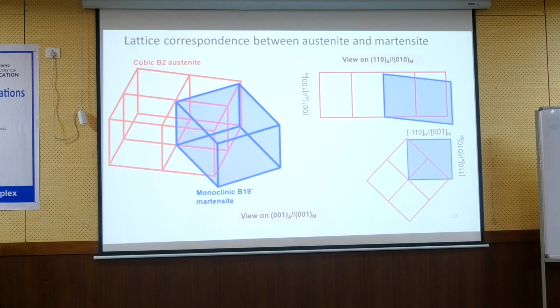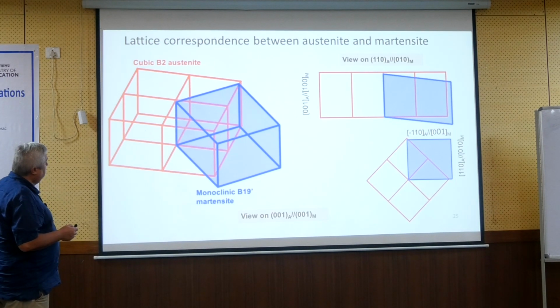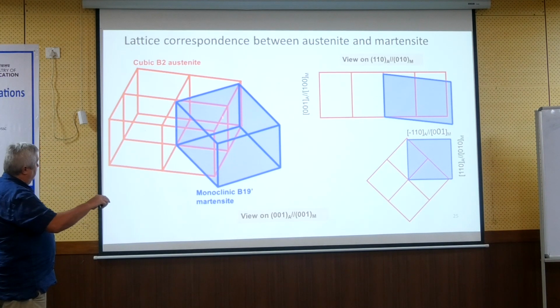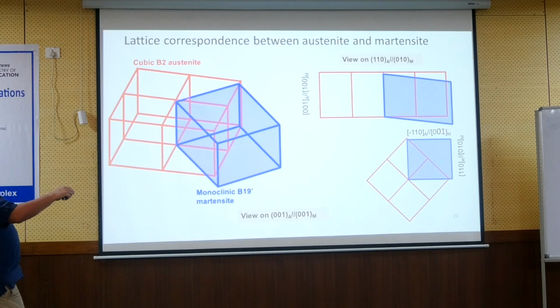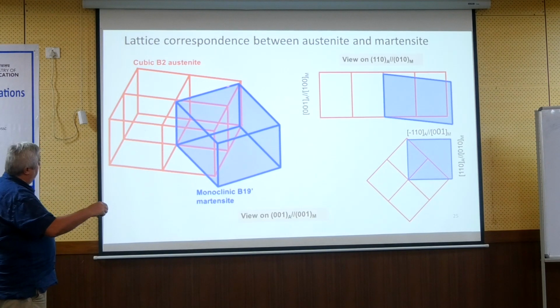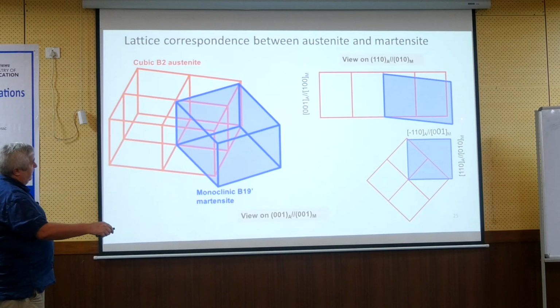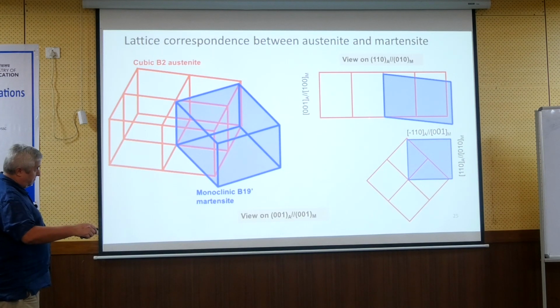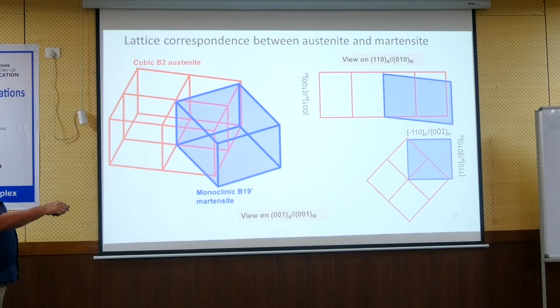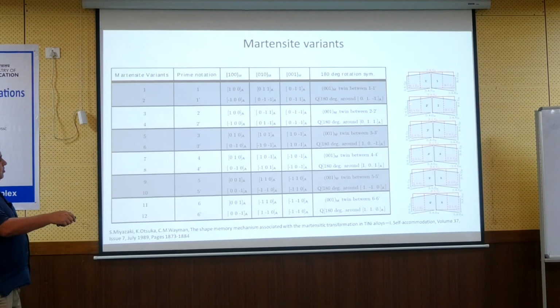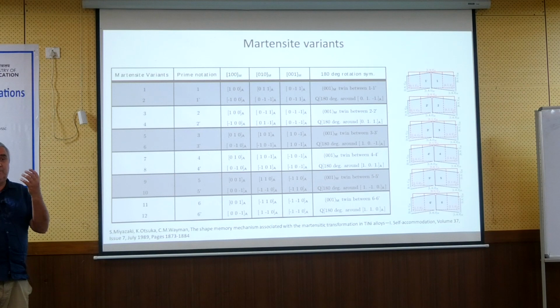So, and maybe I should also say, using this figure. Imagine this is the 011. This is the 011 lattice plane of the austenite, and so it becomes, we call it basal plane of the martensite, and so this is like one twin, and symmetrically here you can have second twin. So from 011 plane you have two variants, and this view is suggested here, that I have 6 011 austenite planes and two variants out of that. So together there is 12 martensite variants which can be created from one cube.